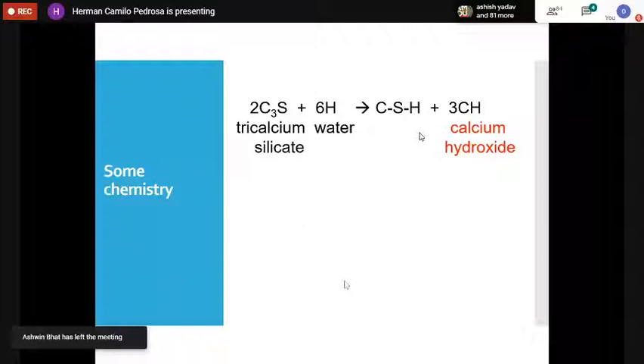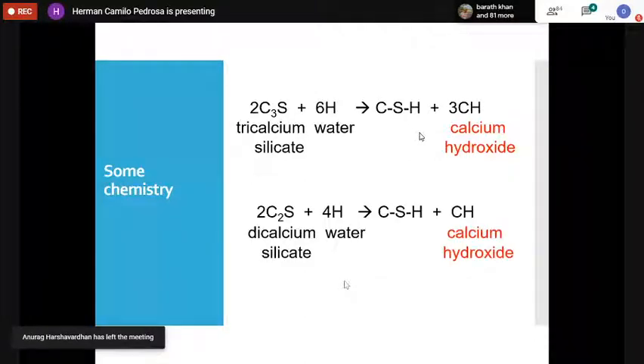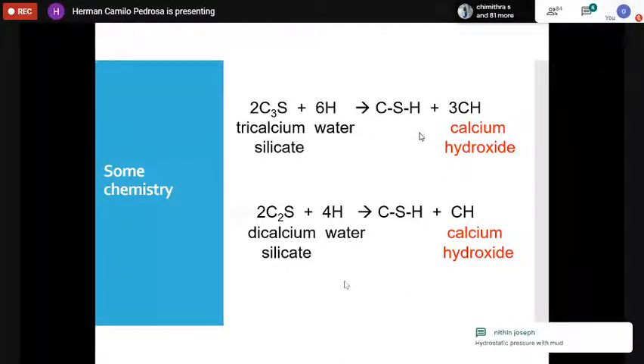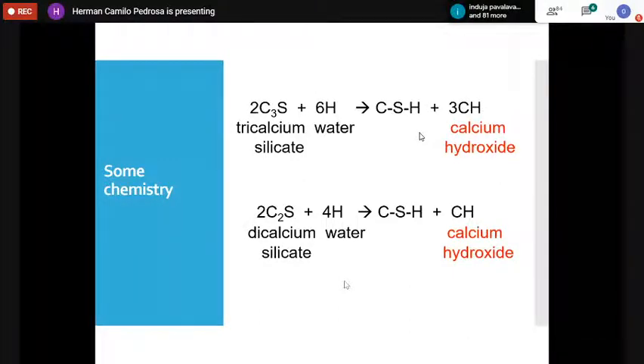So I go a little bit fast through the boring part, or for some, the boring part, which is the chemistry of cement. Mainly what we have, as I mentioned, is tricalcium silicate and dicalcium silicate. They mix with water, and then they start to create CSH, calcium silicate hydrates, and some calcium hydroxide. What will give our cement the strength? It will be the calcium silicate hydrates. That component is the one that will give you the strength in the cement. So the more CSH you have, the stronger the cement. That's the main part.